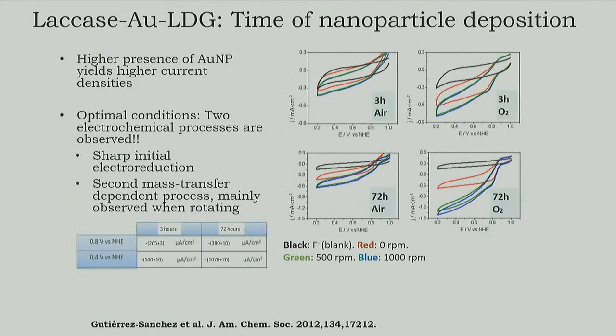And what response we had here, it was really surprising for us, the electrochemical response. We compared different times, up to 3 hours of gold deposition time. When we put oxygen, we were really surprised that this peak appears here, because after 10 years working with this enzyme, I have never seen it before. And what can this be? So we have to study this sharp initial feature and when it appears. And we found out that it appears when a lot of nanoparticles are put there, because it depends on deposition time. We can see this process also when oxygen is supplied as an extra, not just in equilibrium with air.